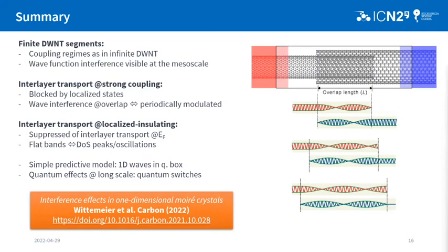And then in the achiral nanotubes, it is a little bit surprising that there's little dependence on the rotational properties, and I don't have a very good explanation why that would be the case. But we actually looked into this multiple times, and we could not reproduce, either with DFT or with the tight binding model, the predictions of rotational dependence on the band structure or the transmission properties.